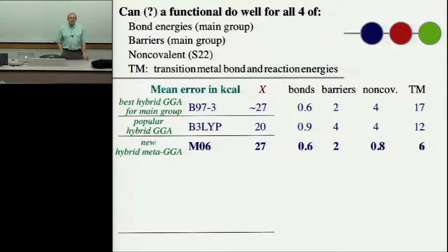But that functional is what's called a range-separated functional. So you take the Coulomb interaction and you take an error function and a complementary error function and you break it into two parts. And you use exact Hartree-Fock exchange on one part of the Coulomb interaction and you use density functional exchange on another. It's a very nice strategy. It's a strategy we're looking into using in our group right now. However, it does limit you on the number of computer codes that you can use because most computer codes don't have that capability to handle that range separation yet. But Scuseria has probably been the most successful on the band gaps.